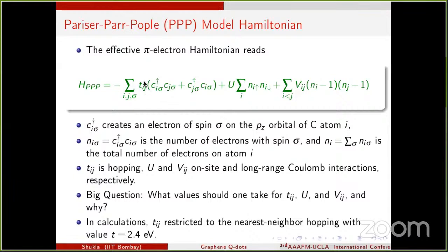So we have hopping matrix elements, then you have Hubbard U, namely the repulsion felt by two electrons if they are on the same carbon atom, and then electron repulsion felt by two electrons which are on different carbon atoms. So hopping, Hubbard U, and long-range Coulomb interactions. But this is not an ab initio approach. Being a semi-empirical approach, we have to come up with reasonable values for these parameters, namely hopping, U, and V. Normally in carbon-based systems, I mean hydrocarbon molecules, hopping is restricted to nearest neighbor and its value is taken to be 2.4 eV.